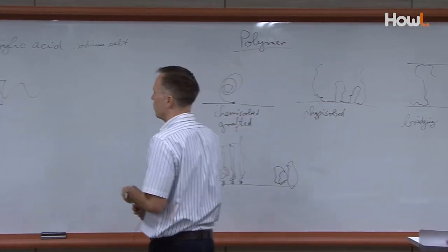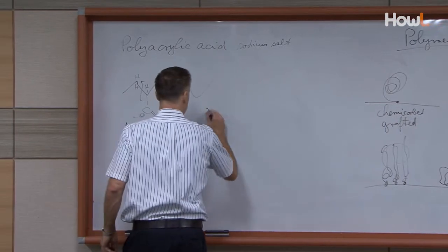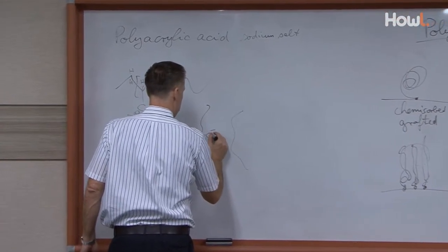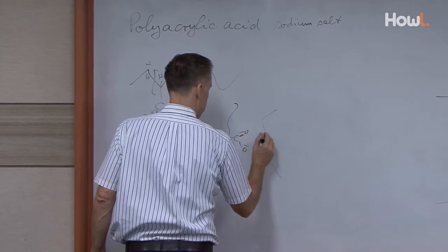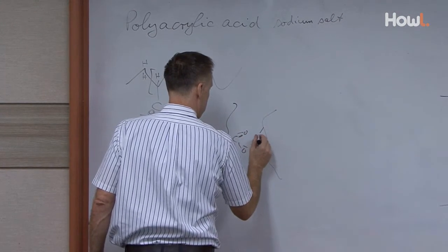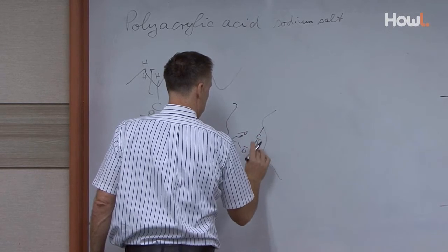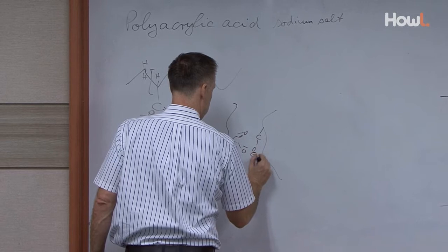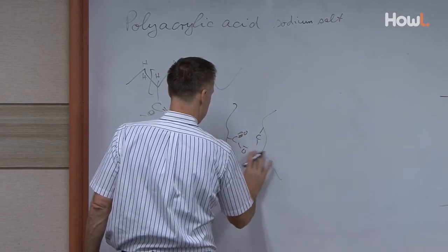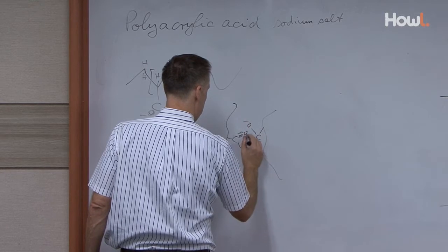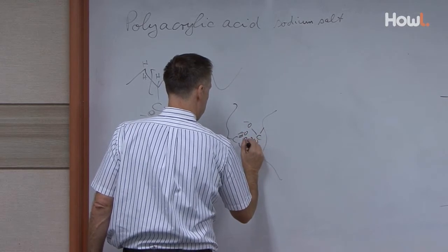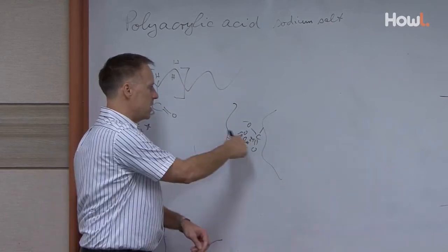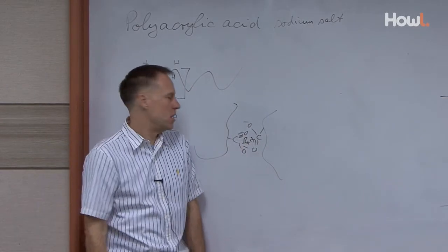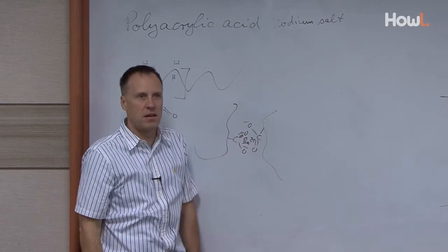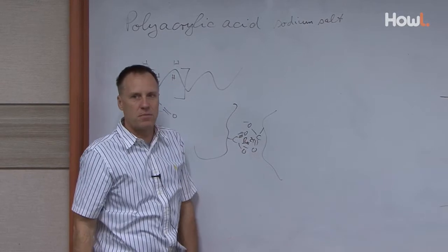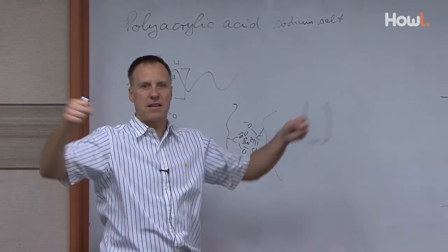But there's another part coming for polyacrylic acid. And that is basically you have two chains here. And you have your carboxylic acid COO minus, and the same thing on this side here, the other way around. And of course, then here, if you have a barium ion in between, you can complex those two. That's similar to the EDTA that I talked to you earlier about. Of course, you only have two groups now attaching to the barium ion, but this cross-links the polyacrylic acid chain, which means the polyacrylic acid acts like it's a higher molecular weight.